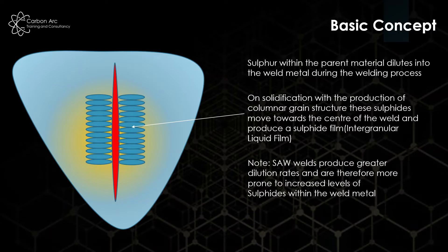And because we're talking about sulfides coming from the base material, really any process that gives us high dilution, something like a submerged arc weld where we have deep and narrow welds, we mix in a lot of base material into a single bead will create more sulfide into that centerline of that pass. So one way we want to get around that is by limiting the size of our welds if we think we're going to have an issue with this type of failure.